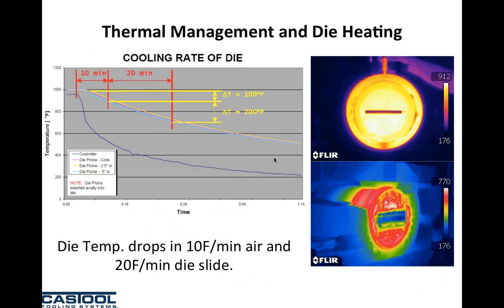Even when you have a perfect die coming out of the die oven, the die can cool down quickly: around 10 degrees Fahrenheit per minute in the air, or 20 degrees Fahrenheit per minute in the die slide. So you're not really getting the temperature that you think you are when you leave the die in the air for too long, or in the die slide for too long. And when you start to extrude, you will see the flow stress get affected because of the die temperatures.